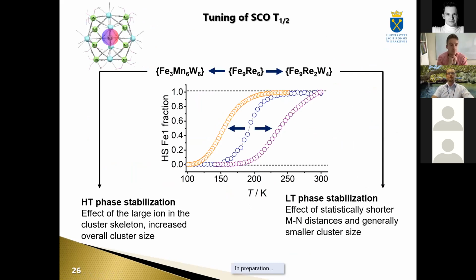composed research is that in iron manganese tungsten phases, we have definitely a high temperature phase stabilization. So this is this curve. This is the curve which is compared with bimetallic iron rhenium phase. Going to the iron rhenium tungsten trimetallic phases, we have the stabilization of low temperature phase, which can be related to the statistically shorter MN distances and generally smaller cluster size compared to this series.